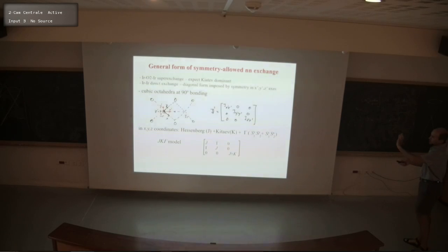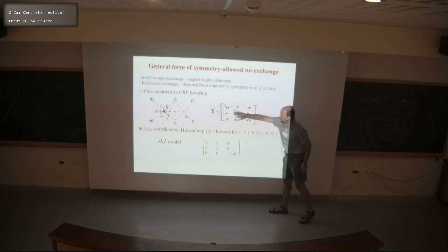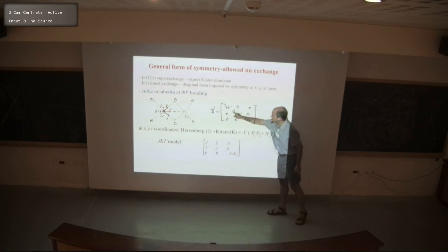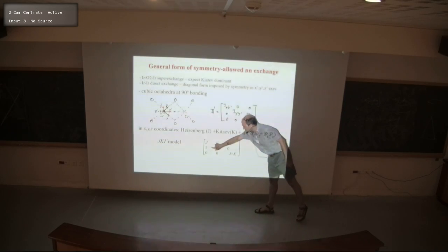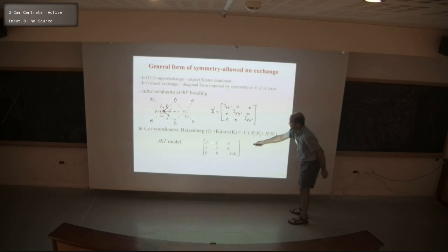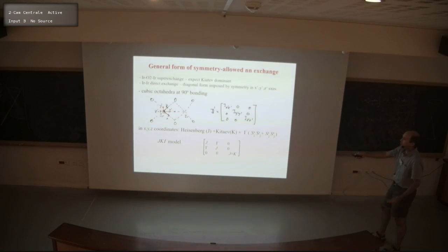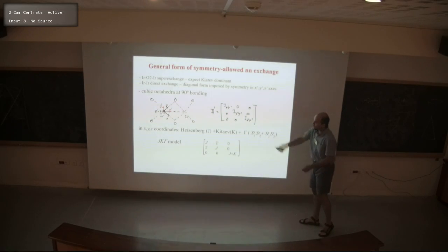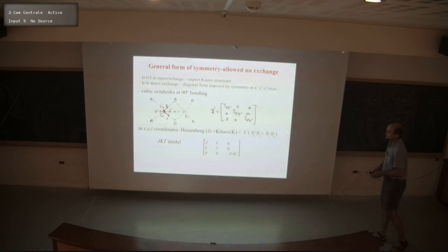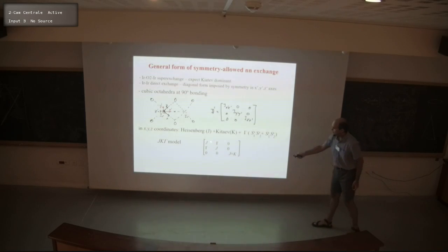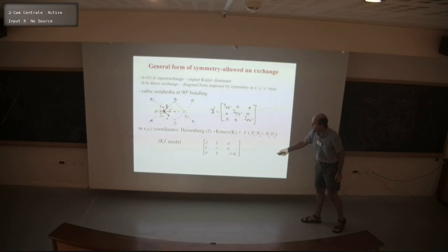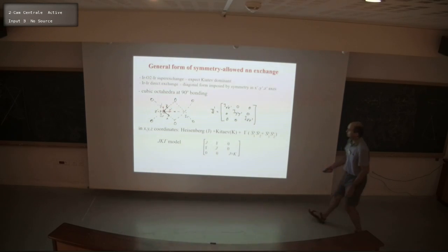However, most of the description is in the cubic axes, which are rotated 45 degrees with respect to these ones. And so in that case, when this matrix is rotated into the cubic frame, then off-diagonal terms come up here that are equal in magnitude. Okay? And these 2 terms become the same. So the most general form for the Hamiltonian, even in the case where this is exactly cubic with axes exactly 90 degrees and so on, not including real material effects such as trigonal squashing and so on. So in the most general high symmetry case, we expect to have the Kitaev term, a Heisenberg term, and also what's called the gamma term, which is a symmetric exchange between x and y couplings.